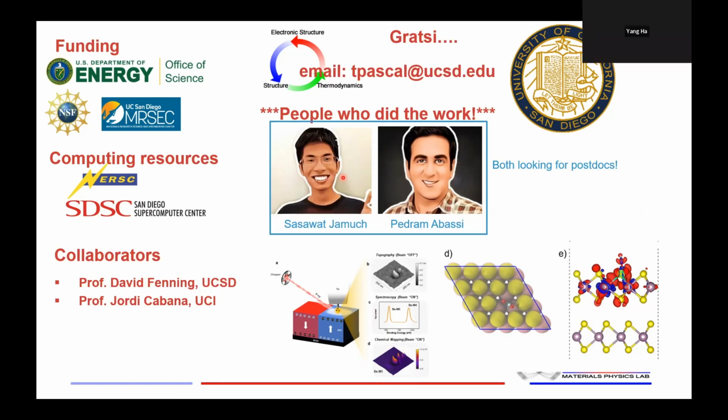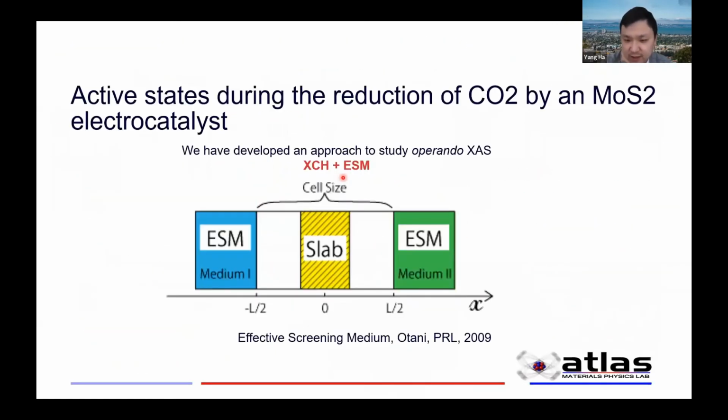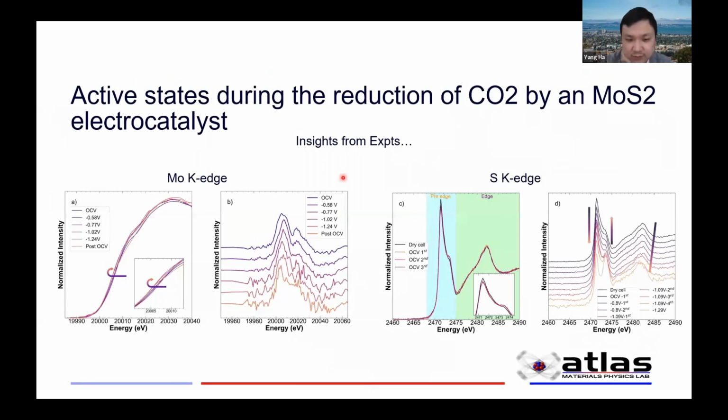Yeah, it's been very interesting, but I'm just curious in your molybdenum sulfide studies, since you collected the sulfur K-edge, usually we would just move about 100 eV above and we get the molybdenum L-edge signal for free, which will give you some electronic information about the system, like maybe CO back-bonding into the molybdenum. I don't know, any comments on that?